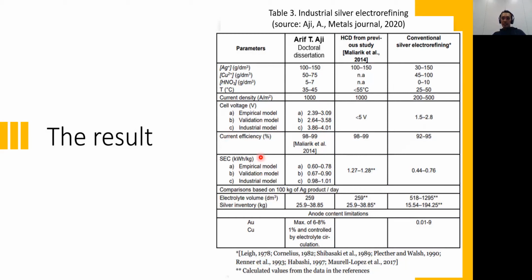And for the current efficiency, I had some difficulties in measuring it at that time. So I took the number provided by Maliarik here, and then calculated further the impact of these parameters on the output of the process. So basically, I'm not really inventing something new. I'm putting more agreement to the fact that silver electrorefining can be processed at high current density without any sort of problem. Even if we have high copper, high gold, high something, we can tweak that process for better production or productivity.